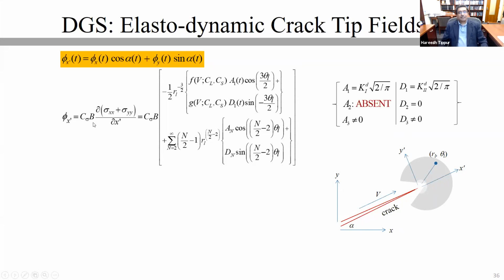Phi-x prime is related to the gradient of sigma x plus sigma y in the x prime direction. In the asymptotic expression that you see on the right-hand side, F and G represent your crack velocities, and A1 and D1 are the leading terms of our asymptotic expression that can be obtained as the two stress intensity factors. So A1 and D1 are connected to the two stress intensity factors.